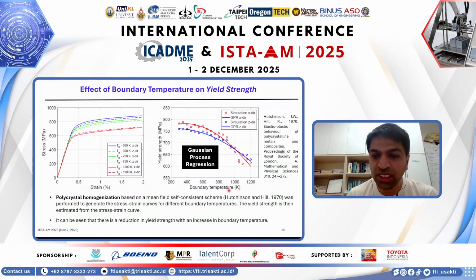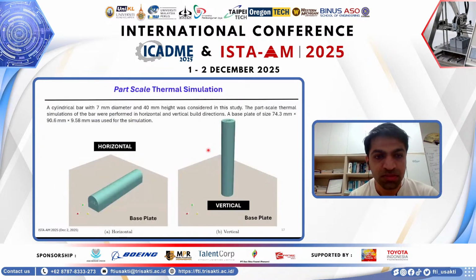The yield strength as a function of boundary temperature is what we show here. You can clearly see that as the boundary temperature increases, the yield strength logically decreases in value. And the trend is of course not a linear trend, but there is a non-linear trend here, and we have used a simple machine learning model called Gaussian process regression to map this dependency, which will then be used later for our optimization routines as well.